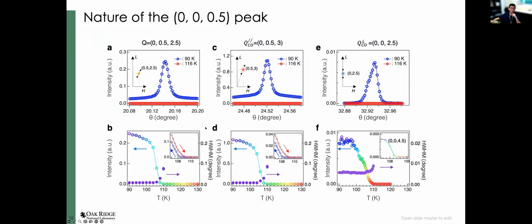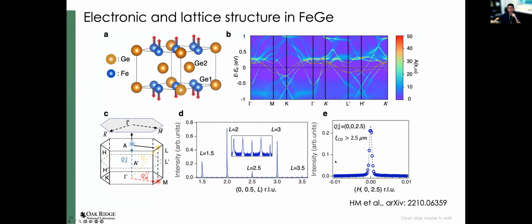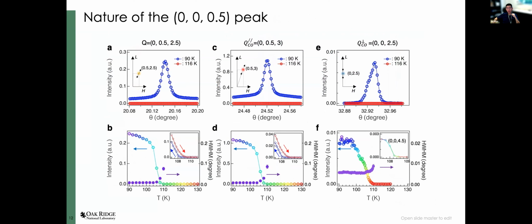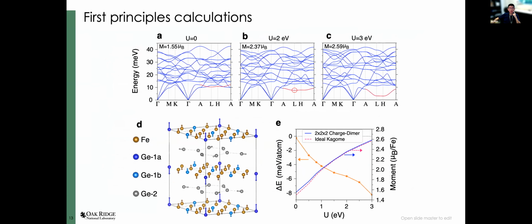So we did a more systematic temperature dependence, tracking the order parameter, and you see both this 002.5 peak and the in-plane 2x2 CDW peak have the same onset temperature. That basically proves that it's indeed a charge superlattice peak associated with the charge density wave. So now the question would be, what's the lattice distortion associated with this 2x2x2 CDW in iron germanium Kagome magnets?